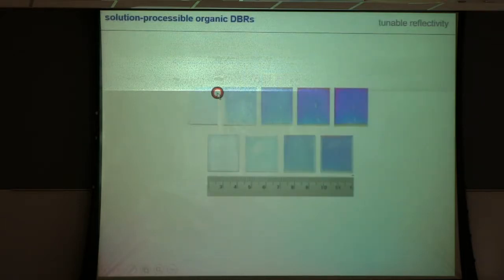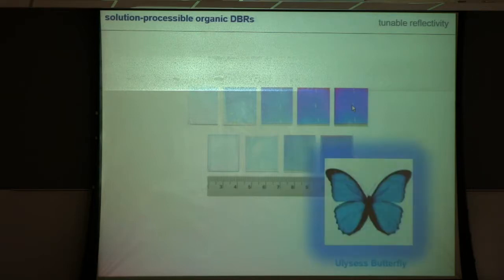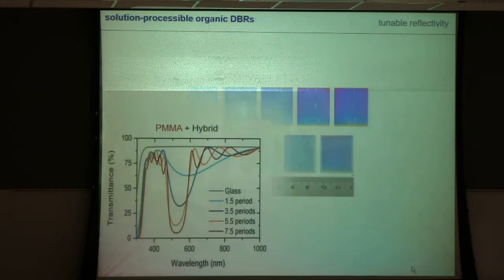And then when we went from 1 period to 2 periods, 3 periods, etc., you see, despite having 2 transparent materials, as you expect, we start to have a mirror that reflects specific wavelengths depending on the refractive index contrast and the film thickness. Very similar to what you find in many of nature's animals, like this Ulysses butterfly. We can, of course, quantify this behavior. Here we use the simple PMMA plexiglass as low refractive index material. It has a refractive index of around 1.5, so we reduce a bit the refractive index contrast.